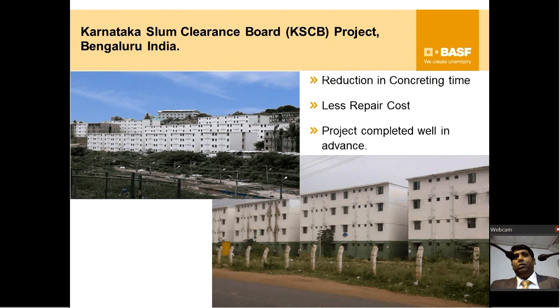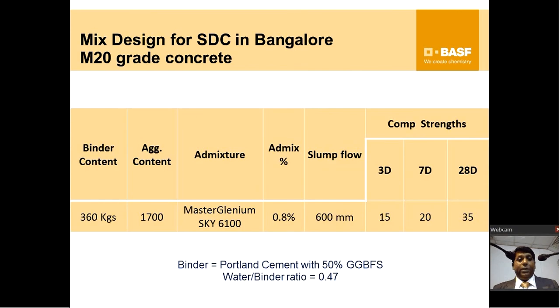The concrete was not specified with SDC or Smart Dynamic. It's a regular concrete that was specified, M20 and M25 grades. But later on, they used this purely because of the cost advantage. Not the cost advantage per cubic meter, but the total overall cost advantage was what they went in for. A typical mix design for M20 in Bangalore has binder content 360 kg. So you could produce a self-compacting concrete with 360 kg cement. That's what this innovation is all about. Provided your sand is good, everything is good, you can even do this with 360.